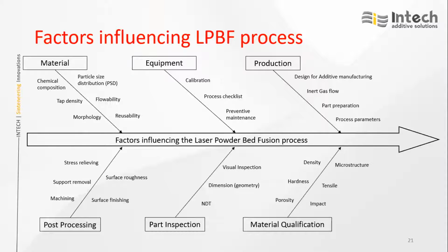Then finally, to qualify a component, along with the actual component, or by printing one actual component as a sacrificial component, we need to take a few samples for tensile and impact testing, or a few portions of the actual component as test plots for characterizing and qualifying by measuring elements like density, hardness, microstructure, and porosity.